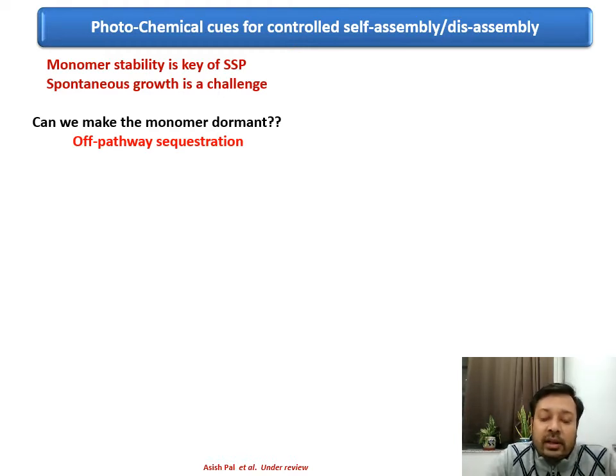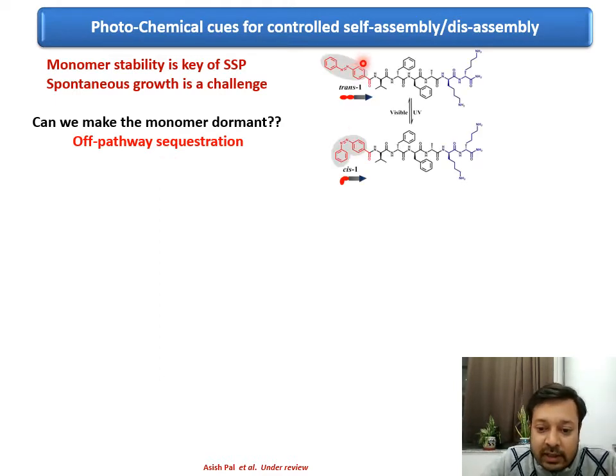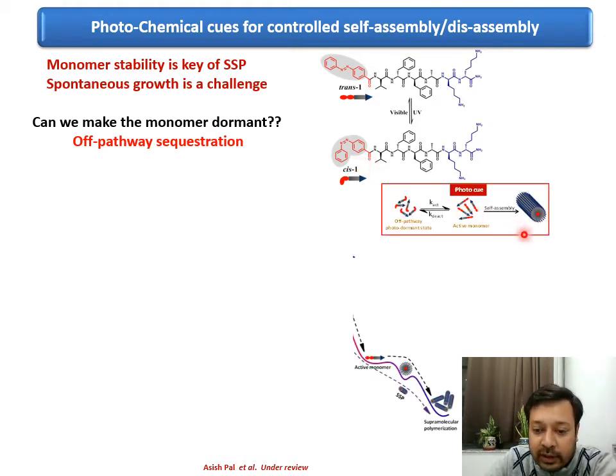So we wanted to really understand how we can control the monomer stability, which will eventually retard the spontaneous growth of the self-assembly process. So we thought, can we sequester that active monomer into something like an off-pathway state, so that as and when we require it, we can activate it and perform the controlled self-assembly. In order to do so, we designed an interesting azobenzene unit onto the N terminus. This azobenzene can be irradiated with light to make the cis analog. With that, we thought that this can be used as a photo cue.